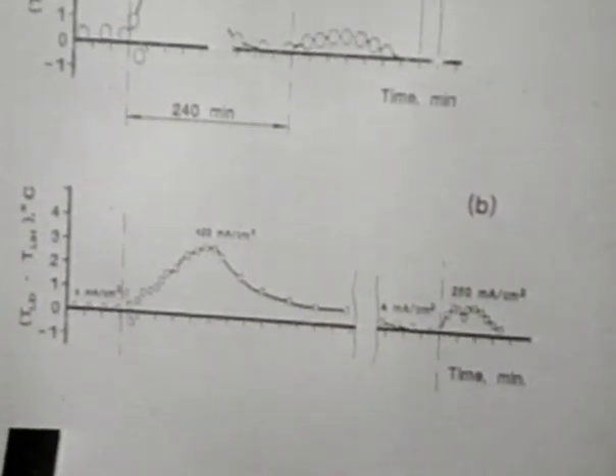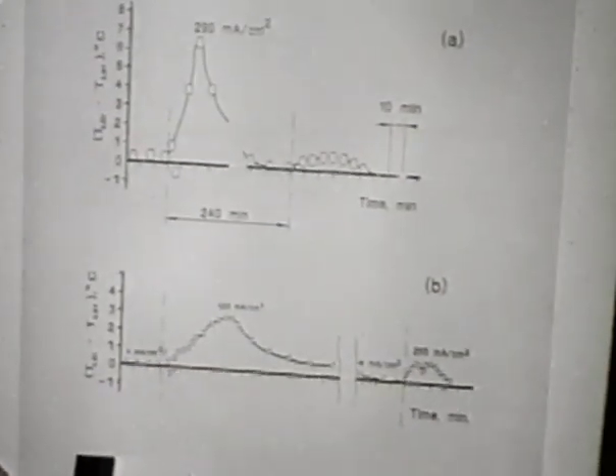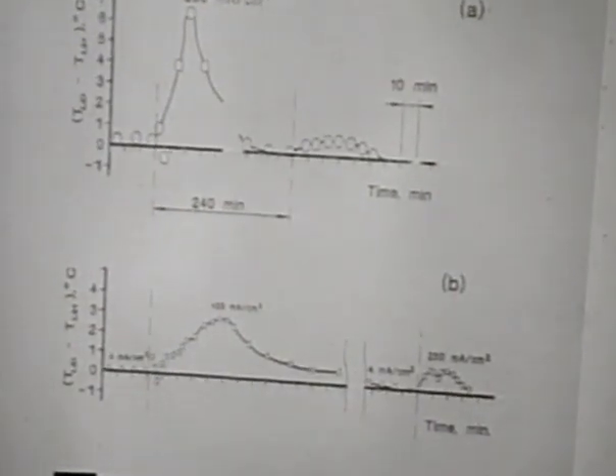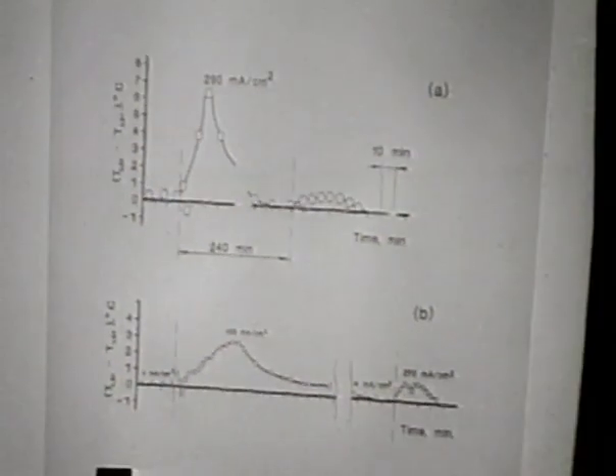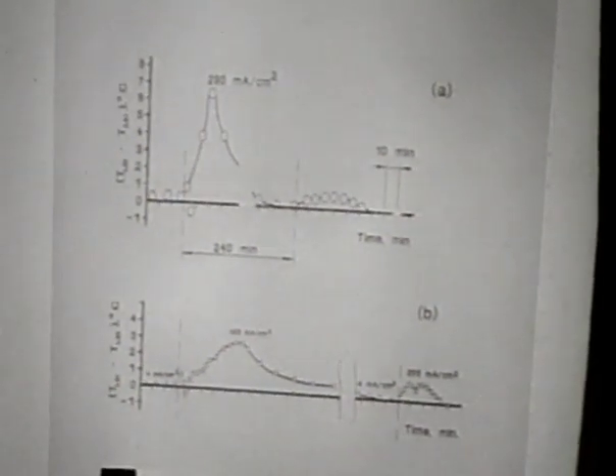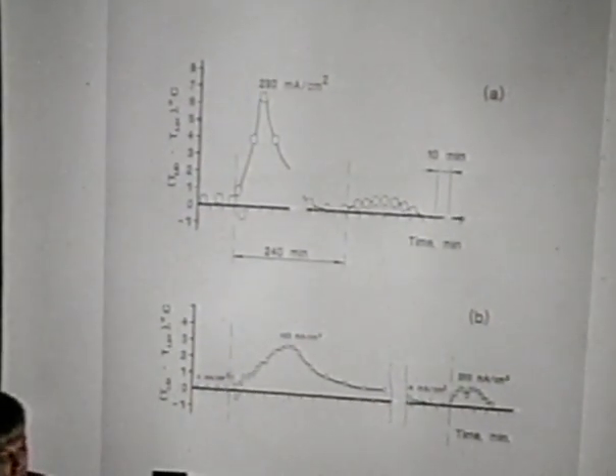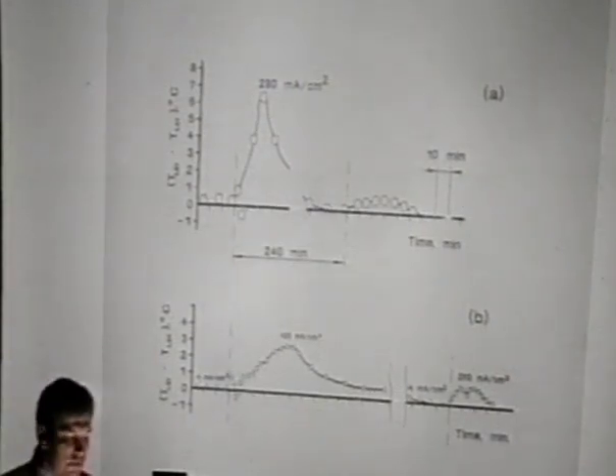This kind of event happened 4 times. What is really interesting is that in this experiment we detected neutron emission strictly correlated to these heat events, which unfortunately we didn't get in the 2 following experiments. We believe the reason is that our first experiment used lithium deuteride in monocrystalline form, which we got from the stock of the Institute of High Temperature Electrochemistry. The 2 following experiments were run with lithium deuteride from Aldrich, which we got from Dr. Liao. So probably the quality of the lithium deuteride is critical.